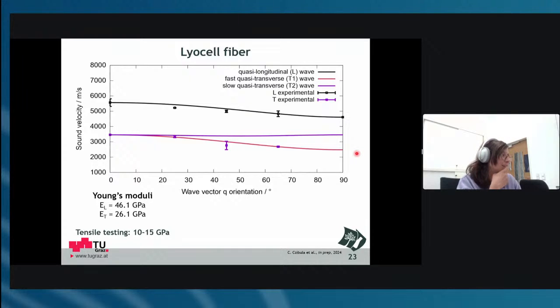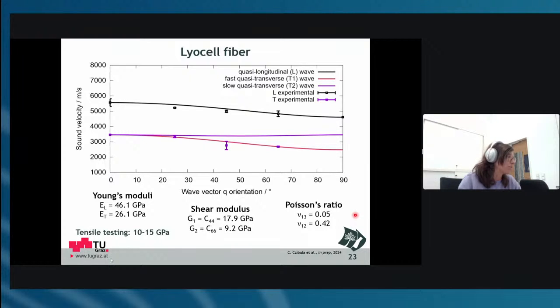Yes. And again, here we also did this evaluation with the mechanical parameters, and the trend is the same as for the viscose. So here we have much higher Young's moduli from these measurements than we get from tensile testing of lyocell fibers. And this is just the tensile tests, so just the literature value. I have not actually evaluated the tests yet from this sort of fiber, and also cross sections I have not looked at yet, but they should be circular, I guess.